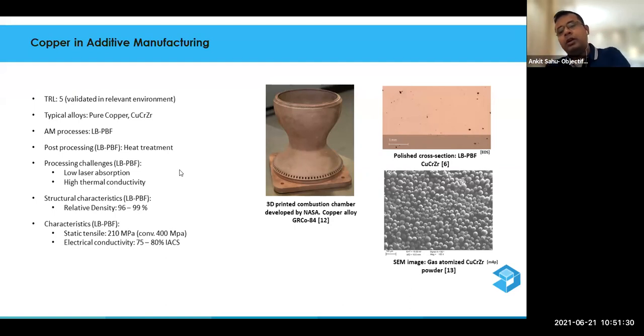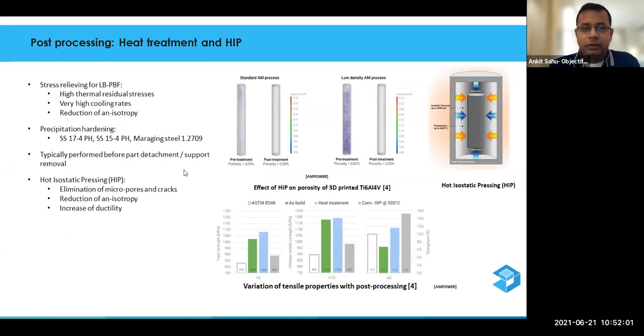depending on the selection of the alloys and at what temperature you are testing. At room temperature, you will have a 95% electrical conductivity, but as you gradually increase the temperature, at 600 degrees we have tested the alloy and it is around 75 to 80%. So it is good enough for a high temperature application, for the electrical conductivity and the tensile properties.